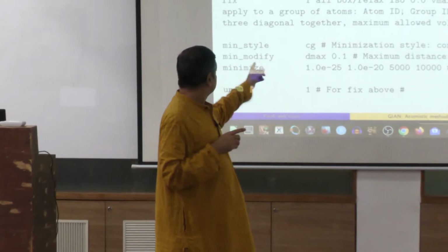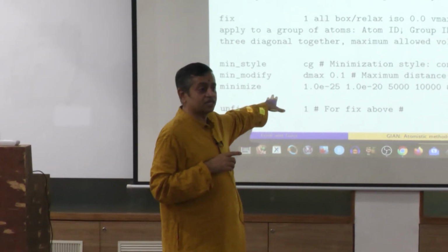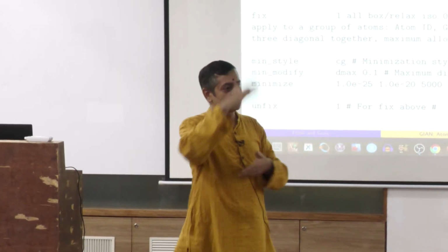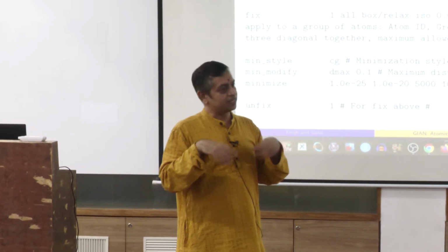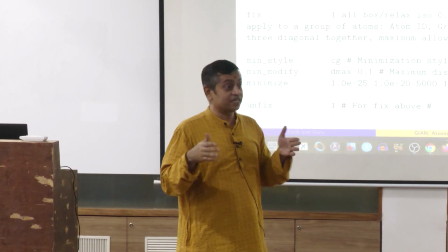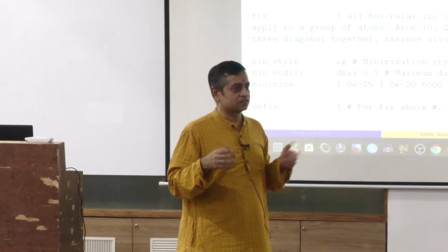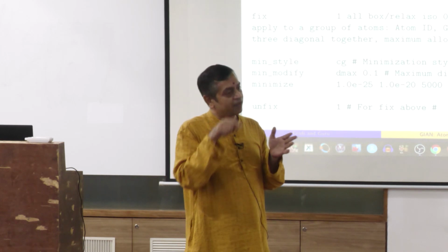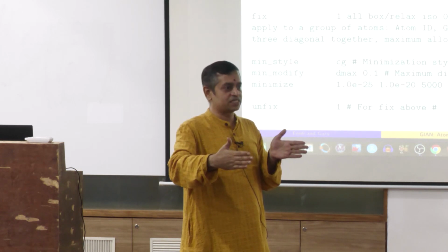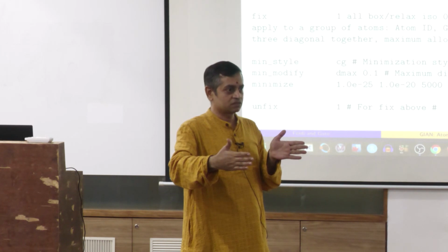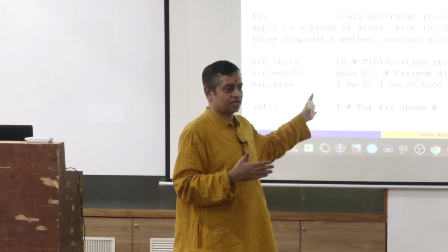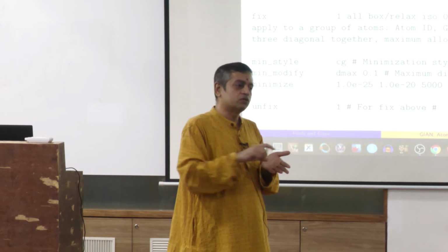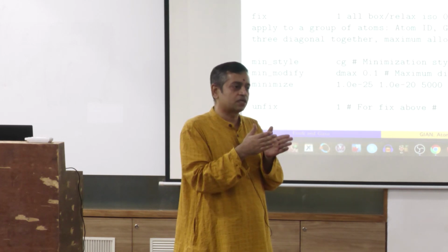But there it is not minimization that tells you. You have to keep the system, measure the Lx, Ly, Lz, and take the average, because they will not be exactly equal; there will be statistical fluctuations. So you take the average and you know how many unit cells are there in your calculation. It cannot be done with one single cell like this here; it has to be done on a larger system. Then you divide by that, and that will give you a lattice parameter.